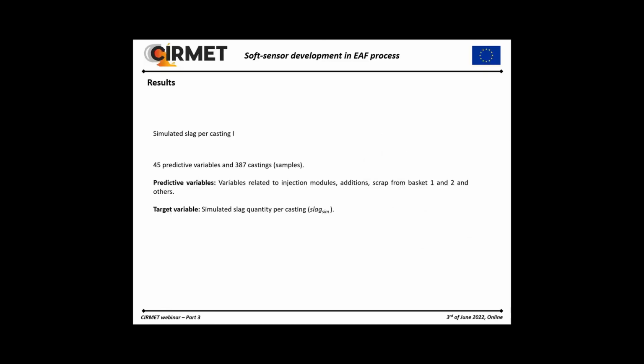Then to do a model per casting, we used the simulated slag in this case. So this was calculated using a mass balance modeling focused on the lime. In this case, we used these variables. So the model was trained with 387 castings and 45 variables.